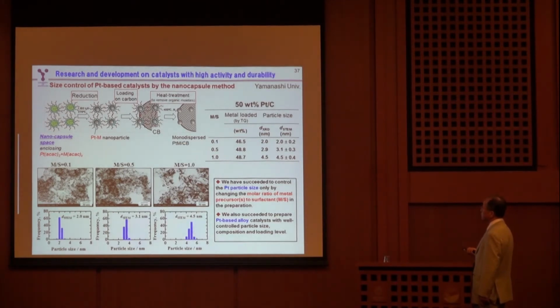We have developed a new preparation method of size-controlled platinum-based catalyst called the nanocapsule method. The platinum precursor is encapsulated into nano-sized micelles, and reduced with a reducing agent in the capsule, and supported on the catalyst support, such as carbon black or graphitized carbon black. And finally, the nanocapsules are removed.